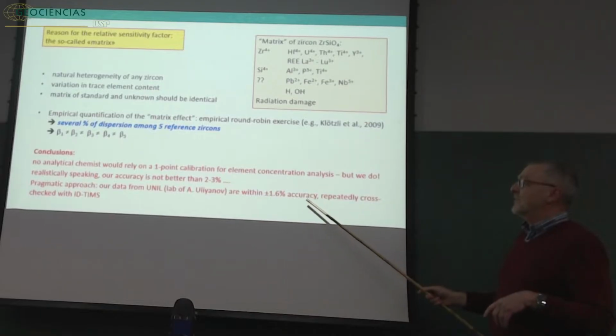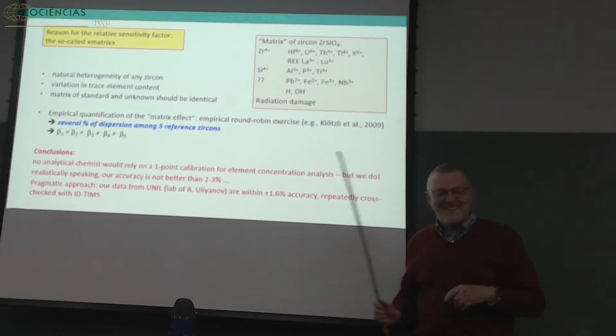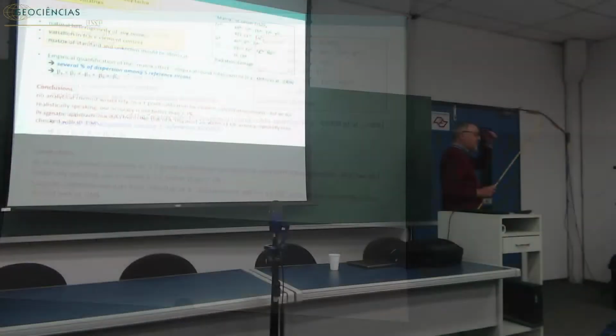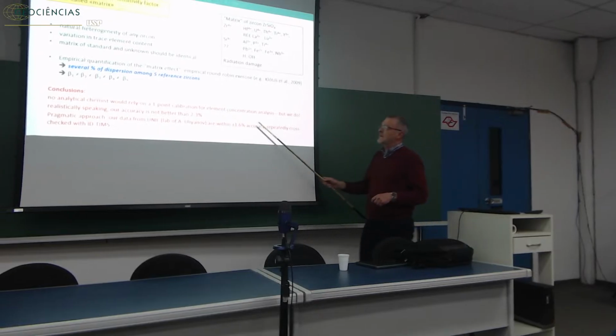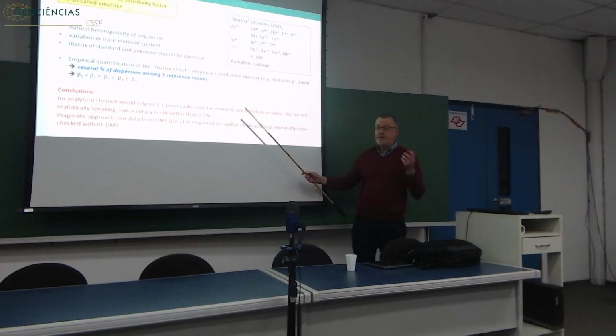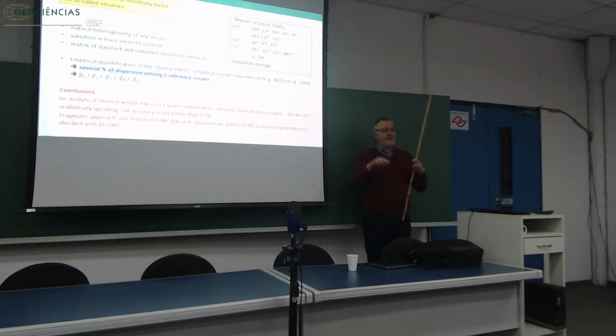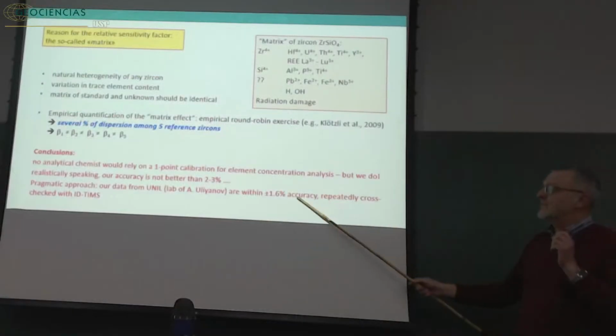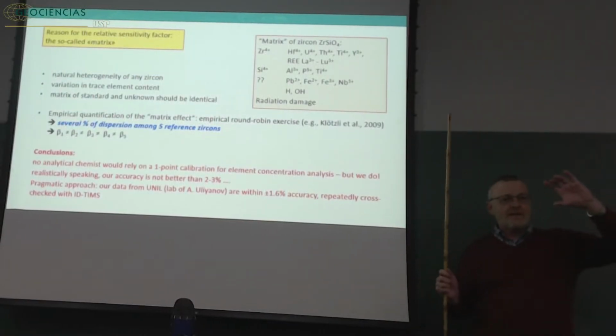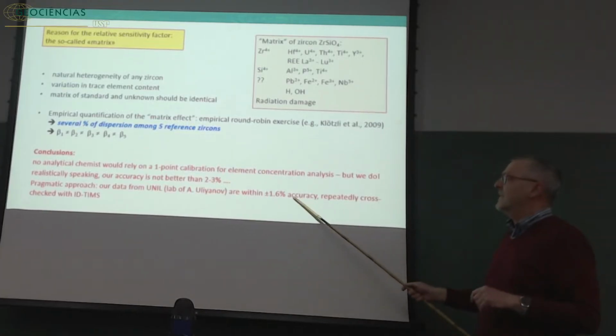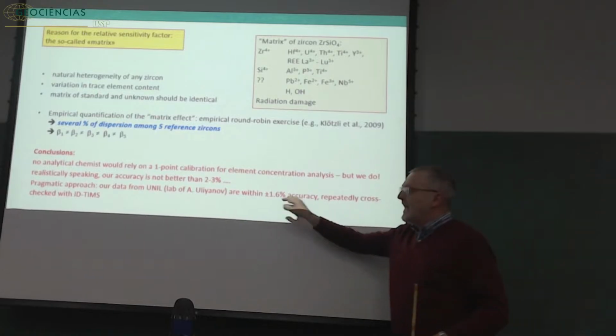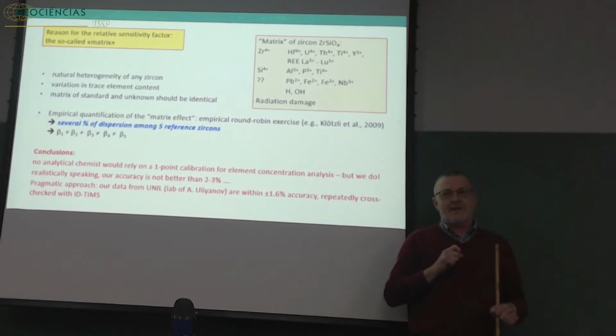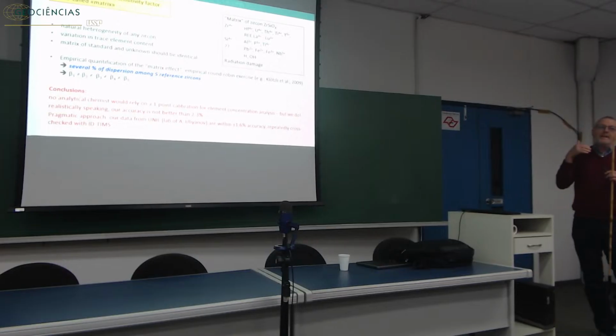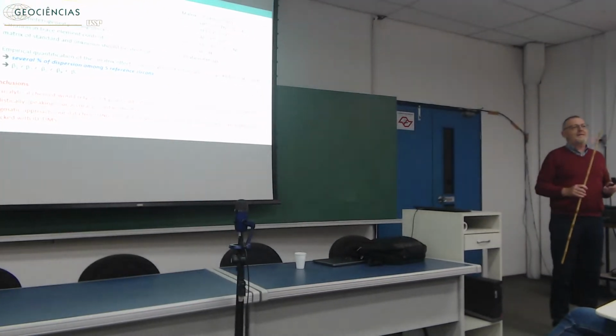And we have derived, with lots of disagreements, we arrived at the conclusion, Alexei and me, that we'll take a very pragmatic approach to this, because between the ICP lab in UNIL, in Lausanne, and the ID-TIMS lab in Geneva, we have done a lot of double dating. And we decided, okay, we are never worse than 1.6% off, so the mean of the laser date with the ID-TIMS. So we take this as the maximum inaccuracy we can accept, plus minus 1.6%. This is kind of our maximum estimate, which we cannot propagate as an uncertainty on our own. There is no mathematical way to do this. We just have to know. We must not forget this.